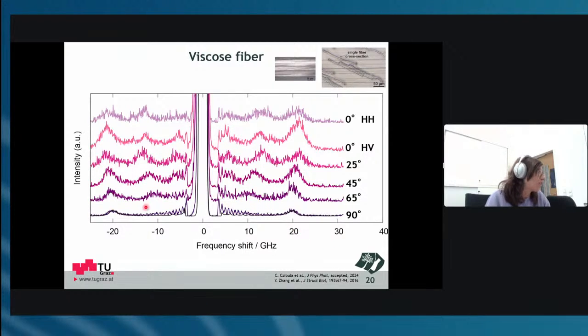So once we figured that out, we could be clear that this is our longitudinal mode. And as you can see, it gets smaller with increasing angles. So the closer we get to the vertical alignment, where we would just measure in radial direction of the fiber, the smaller it gets. And for the transverse direction, it was very difficult to resolve, I must say, because the closer you get to 90 degrees, and the more the orientation of the fiber goes towards being vertical, the higher the scattering from the surface of the fiber is getting.